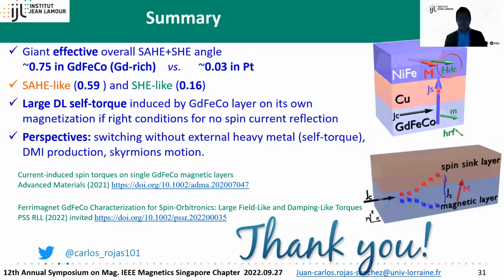And that is crazy. So when we use copper at the bottom and the top, we can keep magnetization out of the plane with thinner and thinner gadolinium iron cobalt. So, for example, if we want to avoid heavy metal, we can use copper. Here we have 10 nanometers of gadolinium iron cobalt, but we can get down to around 4 or 5 nanometers while still keeping perpendicular magnetization, using copper interfaces at the bottom and the top.